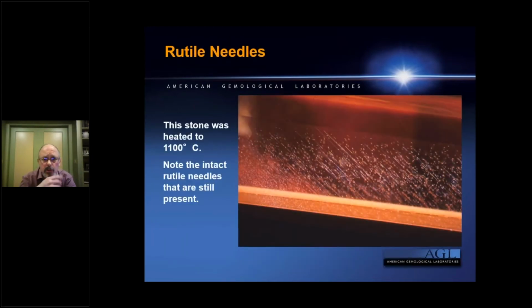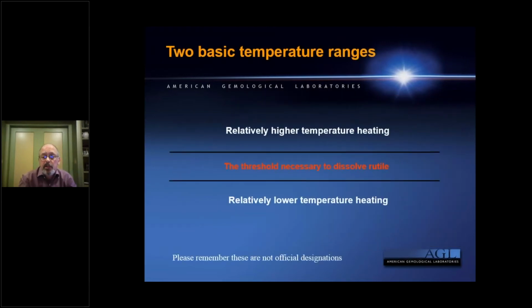And so here I'm also just demonstrating this is a stone that I had heated to 1100 degrees. So again, here you can see the rutile silk, it's very fine, it's all completely intact. I was heating it at a threshold below that to dissolve rutile silk. And so this is now another context which I want people to start thinking about.